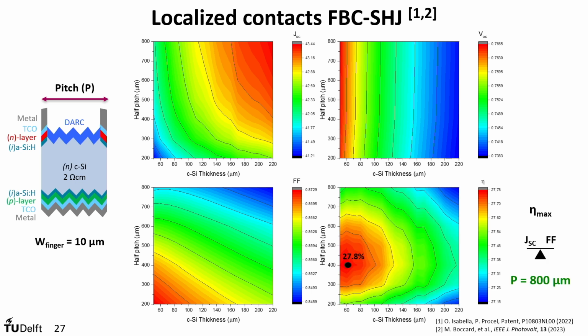So in this case, by combining everything together, we can already predict a 27.8% efficiency with a reasonable pitch, again, fully producible at industrial level without lithography, where JSC and fill factor play the trade-off point, and you only need to choose which thickness you want to work on.